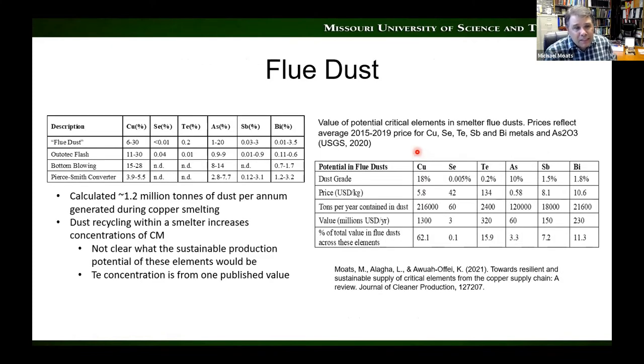With that said, there have been dust samples published in the literature. We estimate from our calculations there's about 1.2 million tons of dust produced per annum from different copper smelters around the world. Most of this dust is recycled, and you can see why. Over here, we calculate a typical dust grade based on the middle of this flue dust, and you can see some prices that we used in our calculations and the amount of tonnage that would be in this 1.2 million. And of course, you can see that there's about $1 billion worth of copper in the dust. So we're going to go after the dust for the copper, because all the other elements are dwarfed.